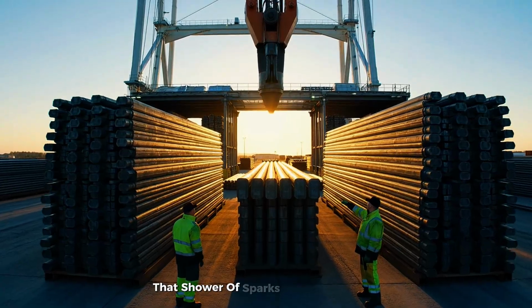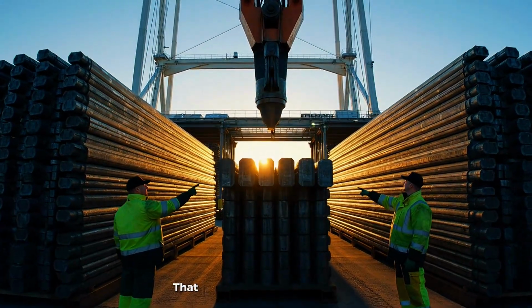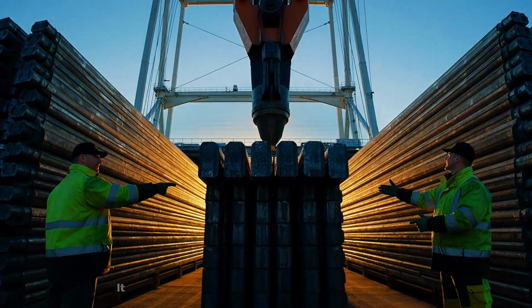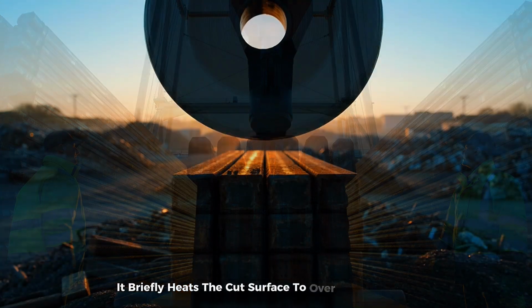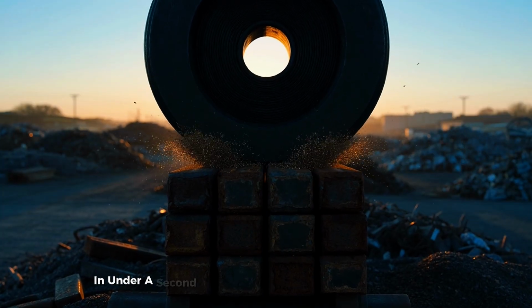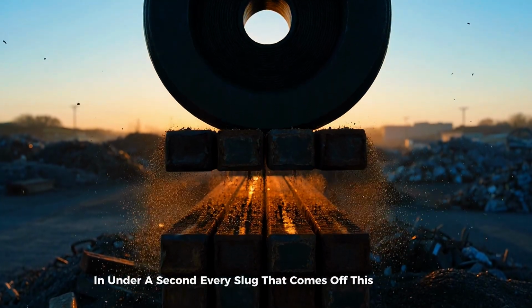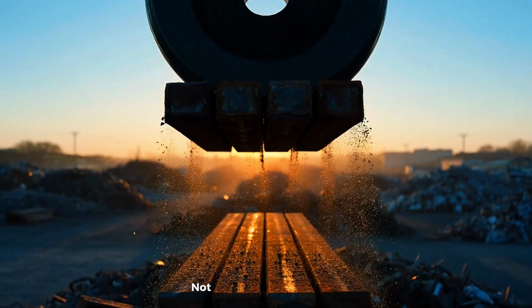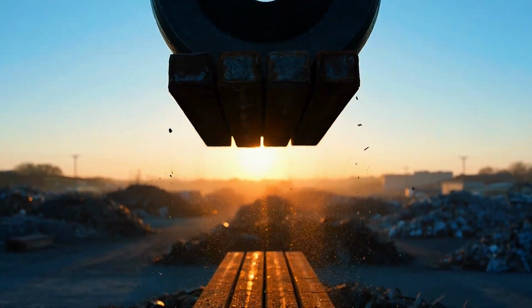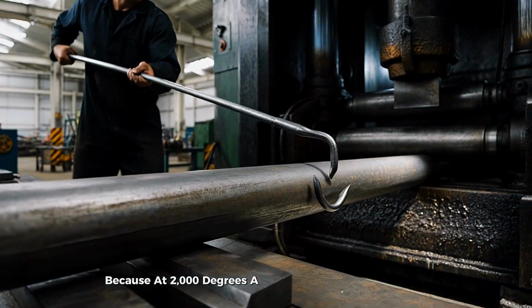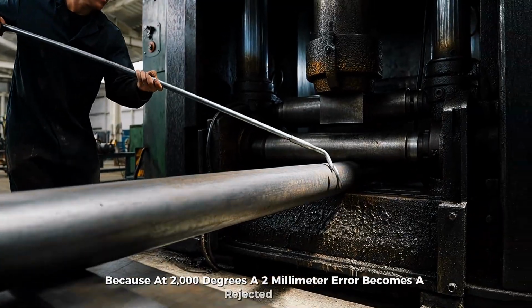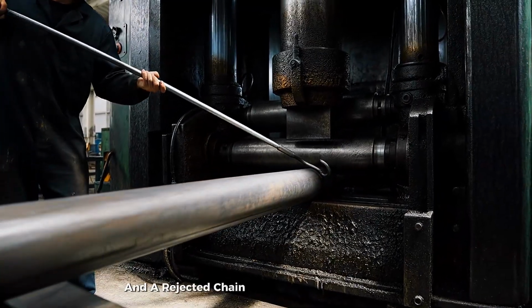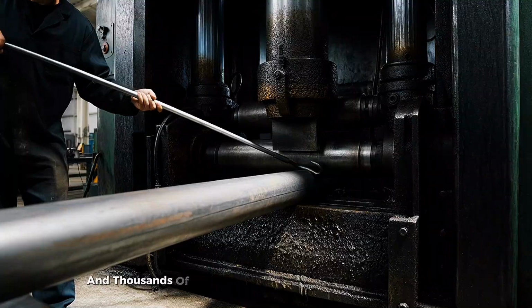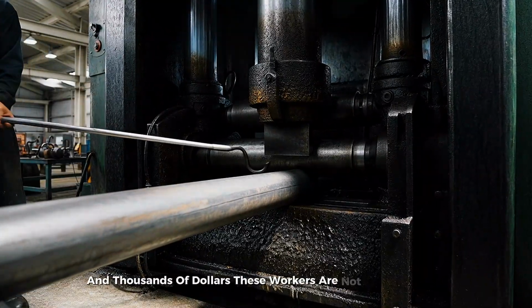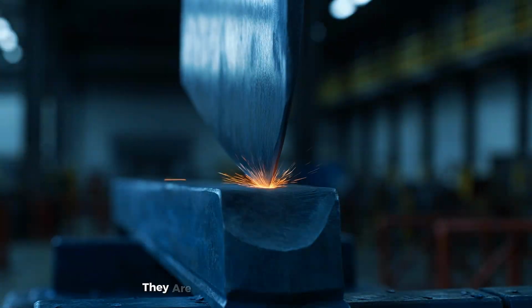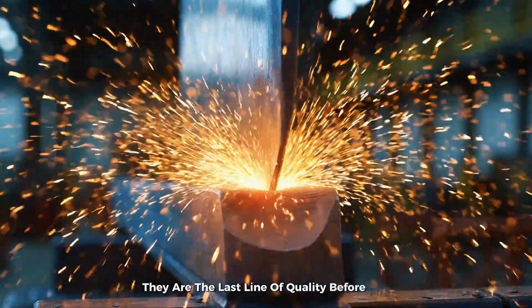That shower of sparks is not decoration. That is friction energy so intense it briefly heats the cut surface to over 1000 degrees in under a second. Every slug that comes off this machine is measured, not approximately, exactly, because at 2000 degrees, a 2 millimeter error becomes a rejected chain. And a rejected chain means wasted days of work and thousands of dollars. These workers are not just checking numbers. They are the last line of quality before fire.